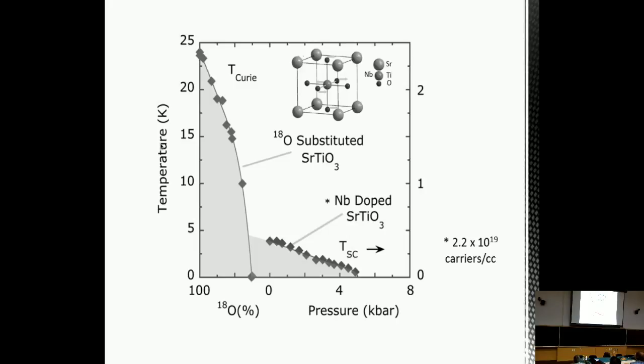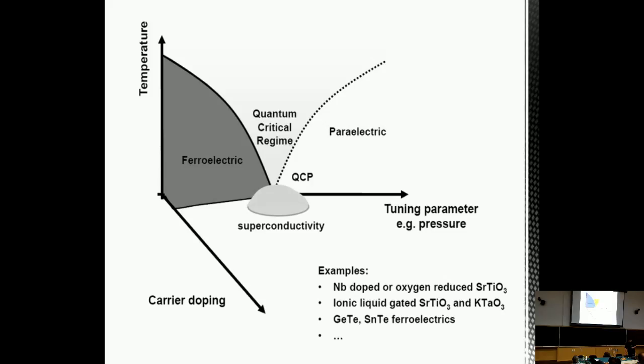And the prediction of the model is that for optimal doping, we recover the same kind of effect, where Tc is maximized close to ferroelectricity. But there's a prediction of the model in the very underdoped side that this will actually go to 0 close to the ferroelectric quantum critical point. So for very underdoped samples, there's a prediction to be tested there.